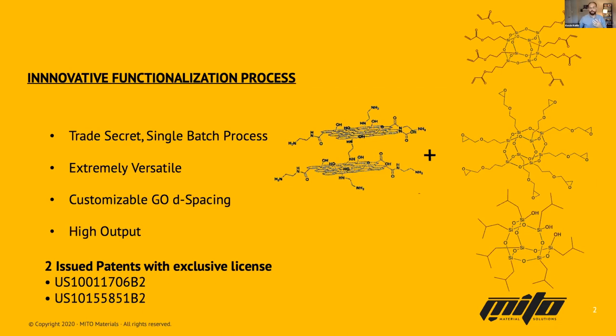It's an organic-inorganic silane cage structure with different polymer functionalization sites, to where you can either have epoxide functionality, methacrylic functionality, and if you want to get really crazy, isobutyl. It is a single batch process that is really versatile, so you can swap out different ingredients. We can actually control the spacing between the graphene oxide platelets, so we can either make them collapse really hard for whatever reason, or you can blow it wide open and keep that surface area extremely wide.